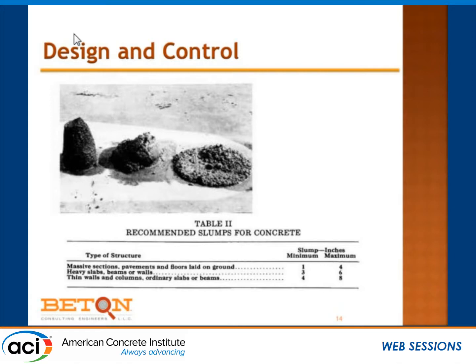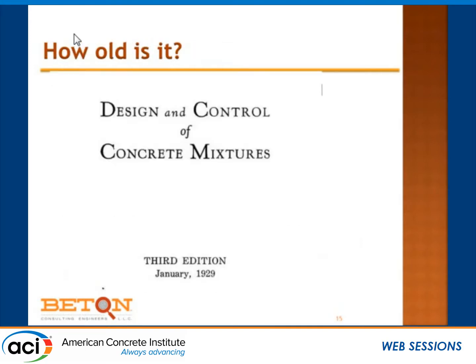And this is not far off the recommendations that you can find in our design codes today. And it's a traditional thing to do, and you should realize that this table I just showed you is from the Design and Control of Concrete Mixtures in 1929. So there are a lot of pieces of information in our codes that are not related to the rate of change that's occurring, because of course I can make concrete that has a 0.30 water to cement ratio and is a puddle on the ground. It would fill this room up, and the concrete in that corner and the concrete in that corner would only be separated by about 1/4 inch without any vibration.